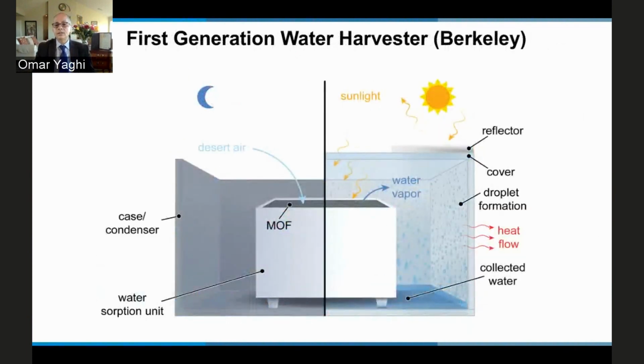So we wanted to show that this works outside the lab in a real environment. And so we built a first generation water harvester made from a box within a box. The small box has the MOF, and the outside box at night is open. So desert air goes into the MOF. The MOF takes up water and gets saturated. During the day you close the outside box, and in the sunlight it heats up. And as the water vapor hits the walls, it condenses and you can collect water.